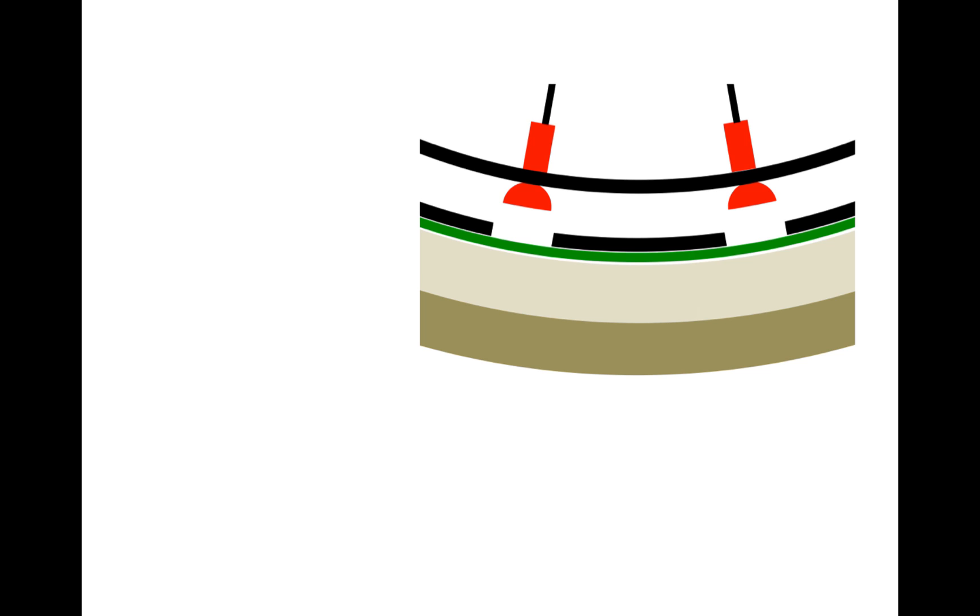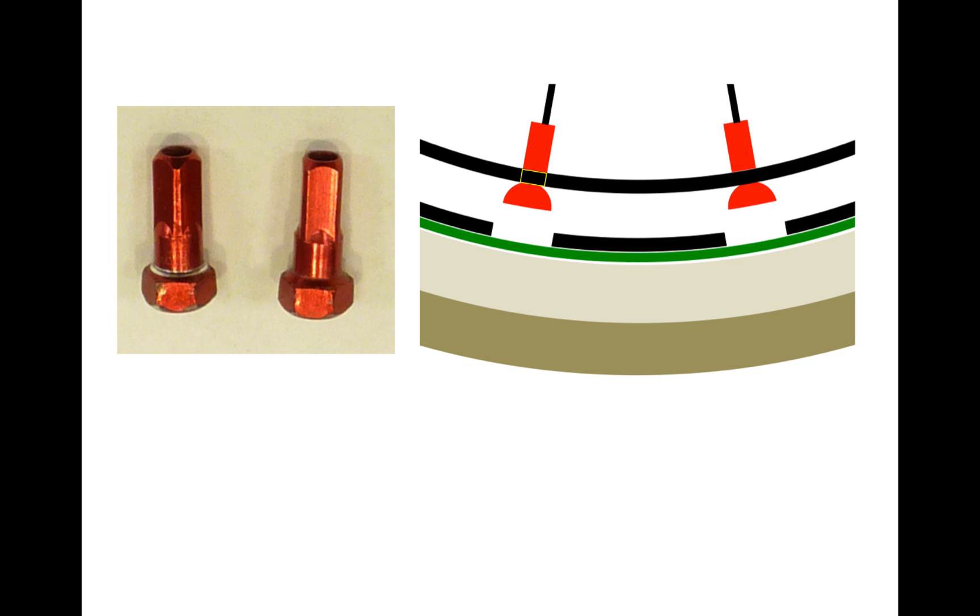Well, almost immediately we start having a problem, because there are holes, of course, through the spoke bed, and those holes have sharp corners. So my nipple starts out looking like this, but after I screw the nipple on farther and farther, getting more and more friction, I eventually will get a ring, as you can see here, where the anodized coating has rubbed off the nipple.